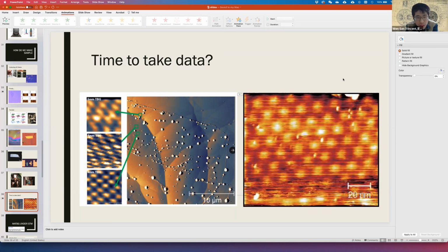Okay, it's dark magic. I'm just curious because we use hydrogen annealing, but in terms of twisted bilayer graphene, I'm not sure if the heat will actually thermalize the graphene, such that maybe you already aligned very well, and after the heat, it might just relax back to the natural state of bilayer. Just curious. Yeah, it's totally possible.